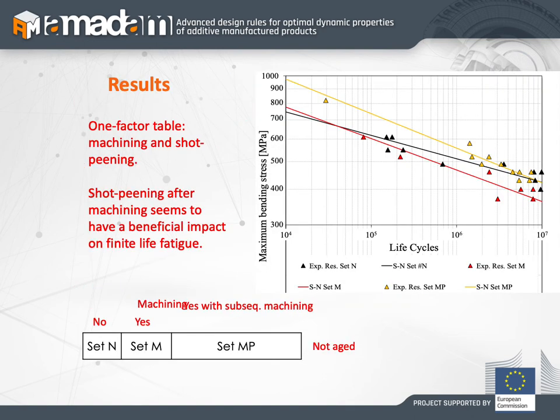In this slide, we now compare the differences between the machined and not aged specimens that are considered before or after the micro shot peening, because normally when the specimens are built, they are subjected to the micro shot peening and then they are machined. That is the case MP in the table.